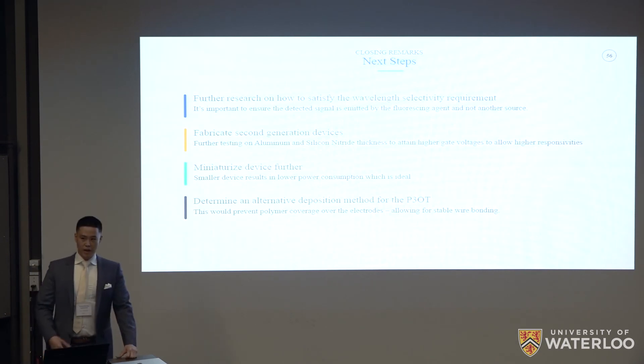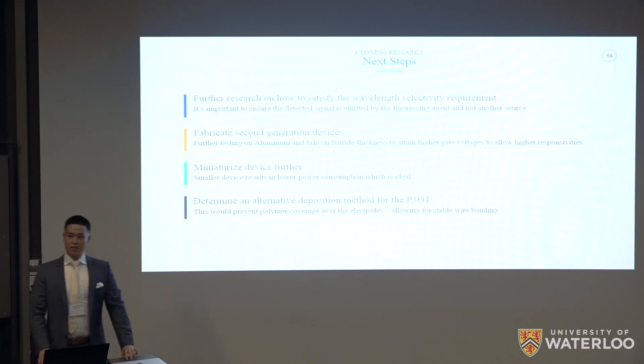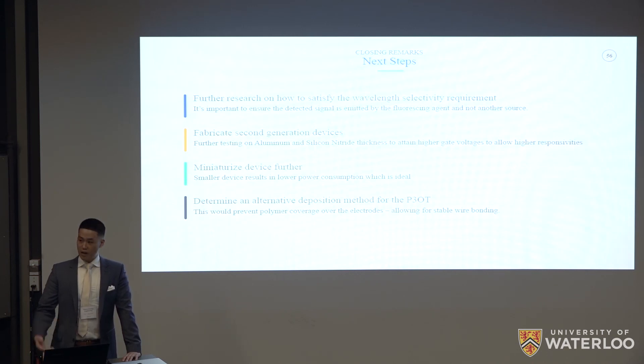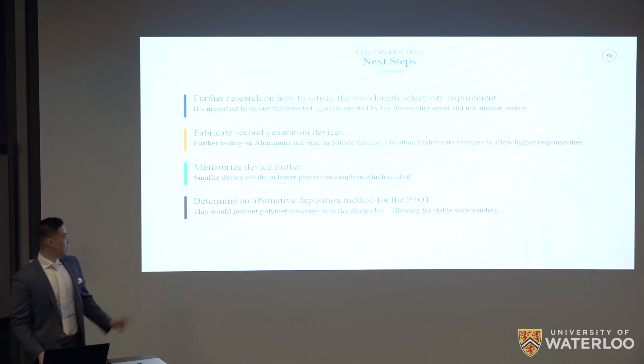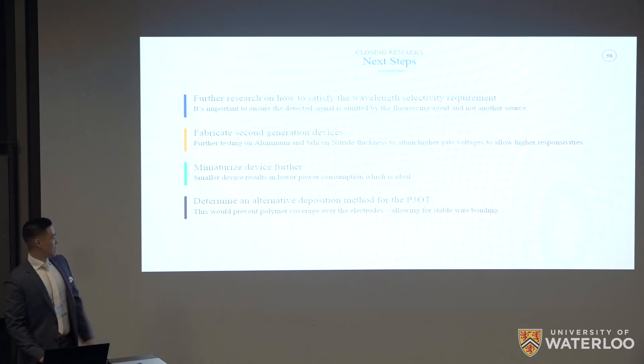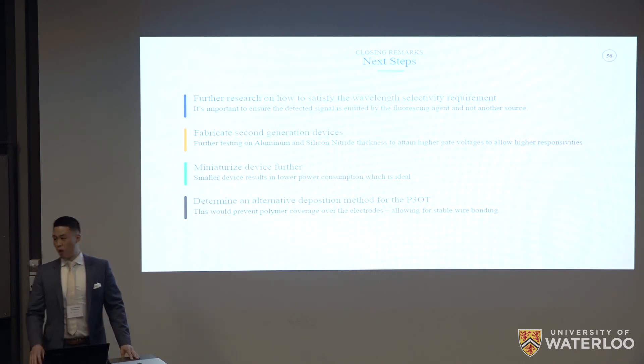Next steps include investigating how to satisfy the selective wavelength requirement, since you need to detect specifically what you intend. We also plan to fabricate second-generation devices to test different aluminum and silicon nitride thicknesses, hoping to enable higher gate voltages and greater responsivity. Miniaturization of the device would help with power consumption, and finding a different way to deposit the P3OT polymer would allow for clearer aluminum electrodes and more stable wire bonding.